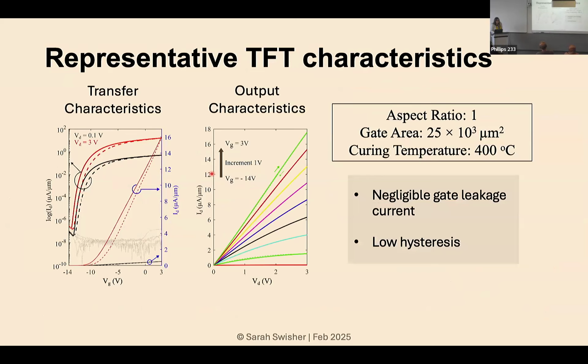So representative TFT characteristics are shown here. This was for a device that was cured at a simulated temperature of about 400 degrees with a gate area of 25,000 square microns and an aspect ratio of 1. So this is one of our square devices. And you can see that the gate leakage here is pretty low because we've kept that temperature to only about 400. And we have some hysteresis in these devices, but not too bad. So this is what a representative TFT characteristic would look like for a device that is cured at a reasonably high temperature.